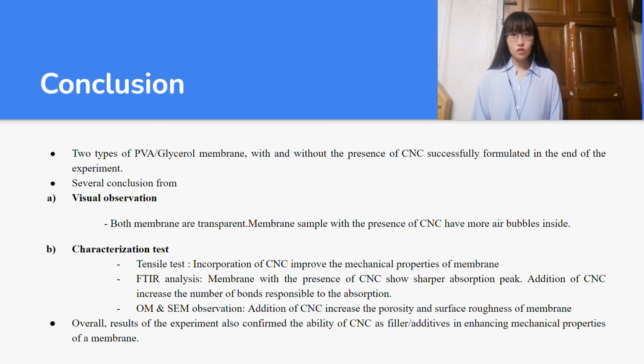So now we have come to the conclusion of this mini project. 2 types of PVA glycerol membranes have been successfully formulated in the end of the experiment through the solvent casting method, with one of them with the presence of CNC as a filler. In visual observation, we can conclude that both samples are transparent, while membrane samples with the presence of CNC have more air bubbles trapped inside.